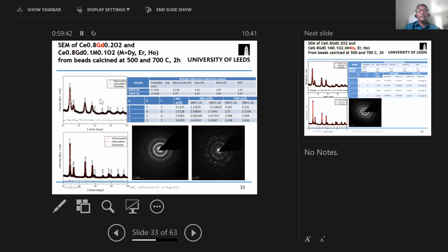So from the TEM, these are the TEM images of 500 and 700 degrees Celsius on the right. The spotty image here of 700 degrees Celsius clearly indicates that there is crystal growth at 700 degrees Celsius, compared to the diffuse ring pattern that you see for the 500 degrees Celsius product. And what you see here is the XRD data, or the interplanar spacing for different planes, HKL values of different planes, matches very well with the TEM data. Of course, the XRD data is much more resolved compared to TEM. And there'll be greater error in TEM measurement compared to XRD for obvious reasons.